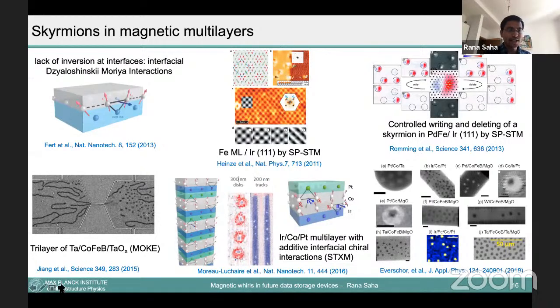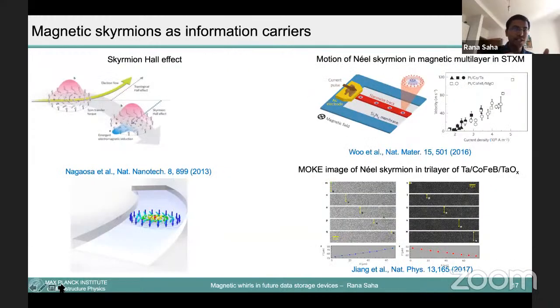As I said, you can use a current to move these skyrmions, but how can you read them? You know the Hall effect. Basically you pass a current in a magnetic material, you have a Lorentz force, and you can accumulate charges, develop an electric field, and read the Hall voltage. Similarly, when an electron passes through a skyrmion material, what happens? It gathers some kind of inner magnetic field and gives rise to some kind of Hall signal. That's how you can detect the skyrmion.